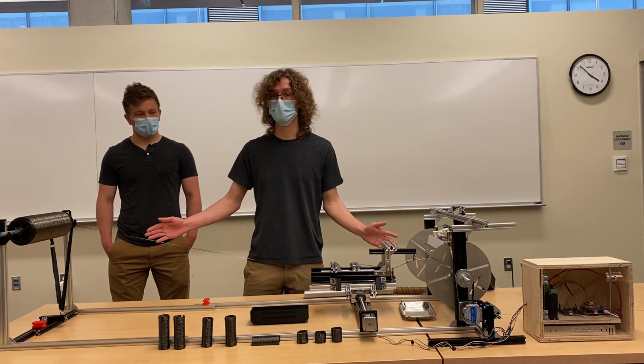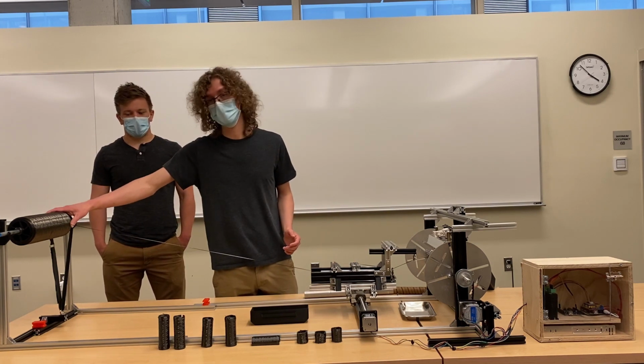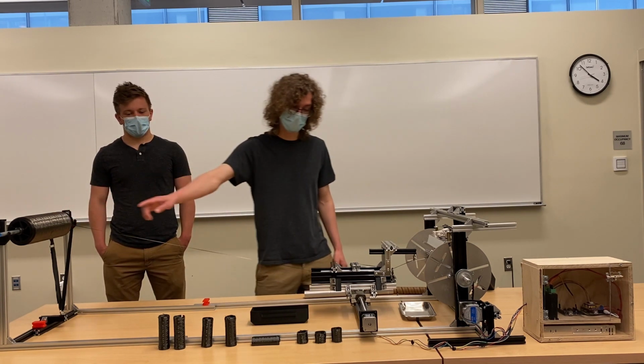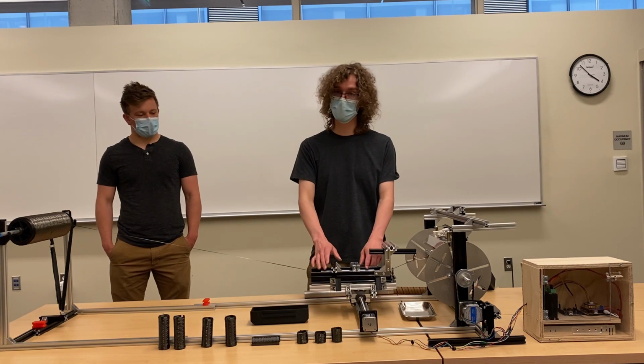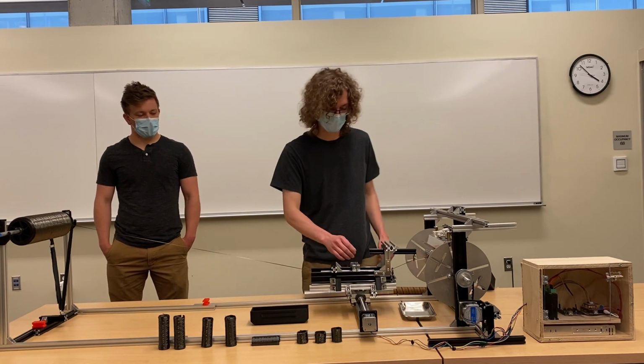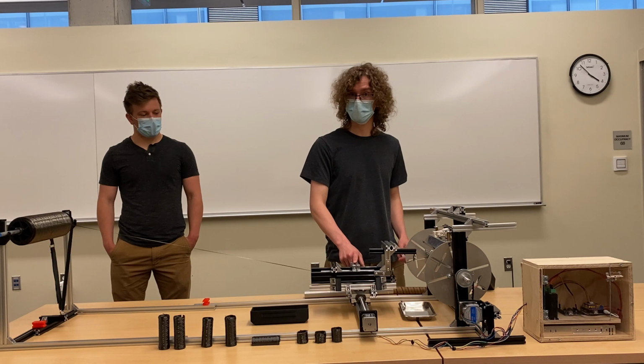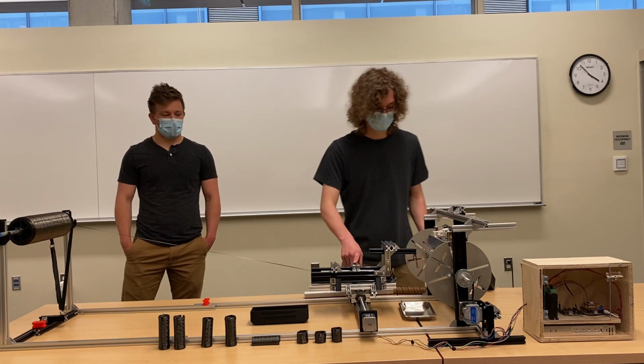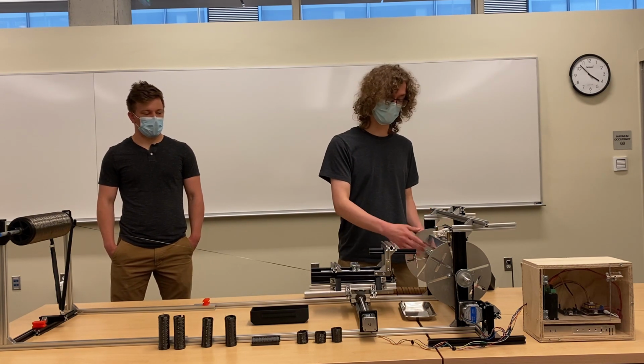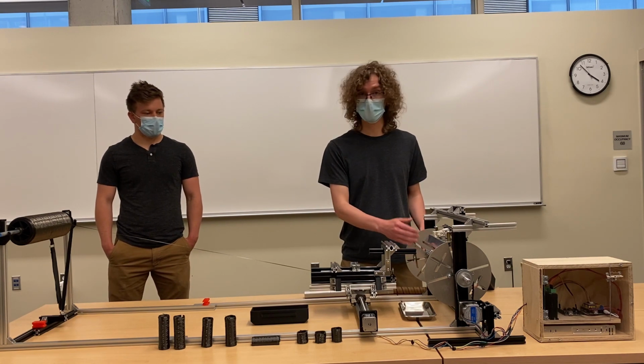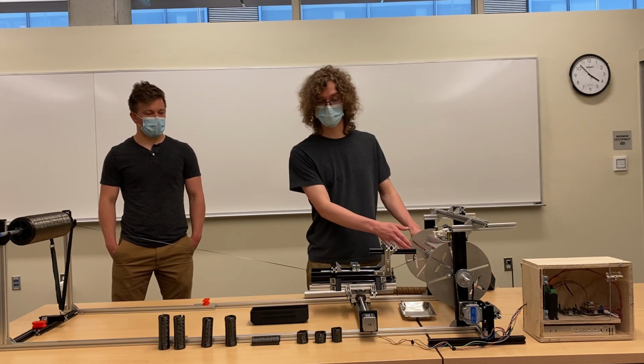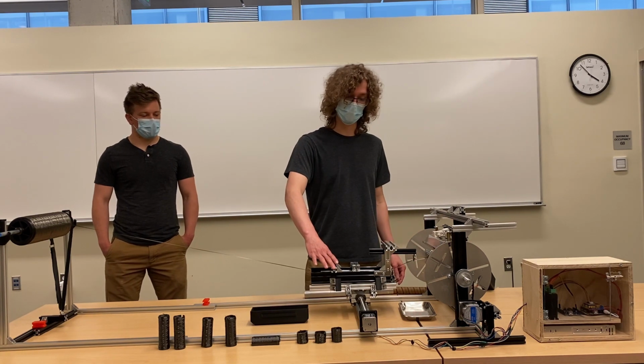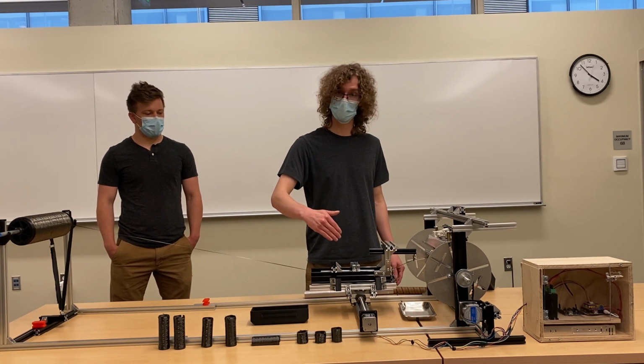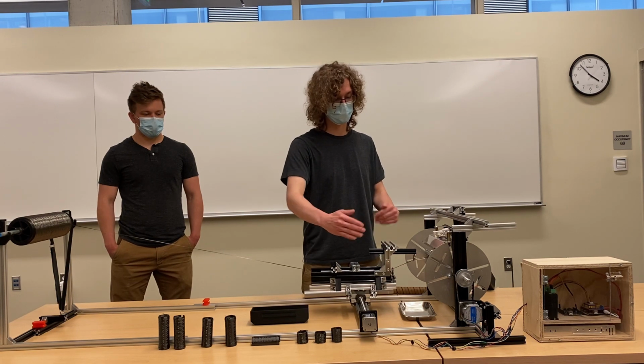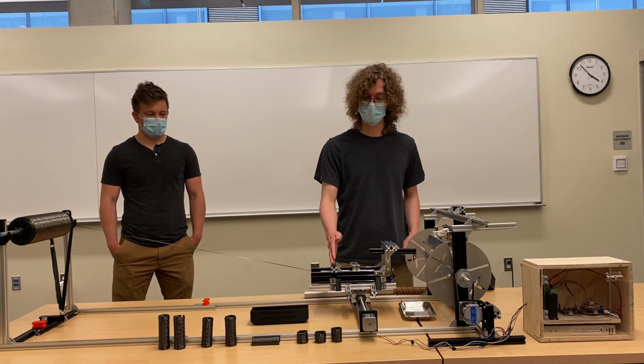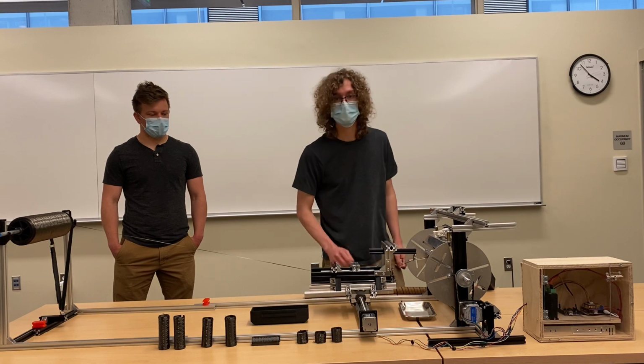On the filament winding machine that we designed and created, the fiber starts on a creel. It is then pulled off the creel and through a resin bath containing the resin. The fiber then passes through nip rollers that remove excess resin. After this, the coated fiber is wrapped onto a rotating profile called a mandrel. While the mandrel is rotating, the resin bath platform actuates left and right so that a specified tube length is created. This continues until a desired tube thickness is reached.